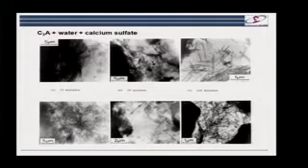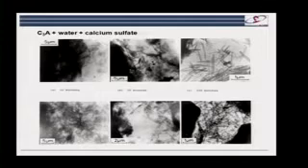So we're going to see what that means in terms of microstructure. So here's some pictures of the reaction of C3A. These are taken in the wet cell in a transmission electron micrograph, so they're as near as possible to undried samples we can really have. And what you see here, here's your C3A grain, here's your ettringite crystals. We can actually see that close to the surface there's some other kind of crystals.